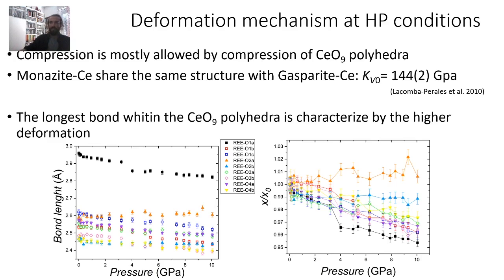The two diagrams here reported show the shortening with pressure, on the right normalized, of the RE-oxygen bonds. It is clear that the RE-O9 polyhedron is a distorted polyhedron better described as an 8+1, and because of the RE-O1A bond length, this is also the most compressible bond.